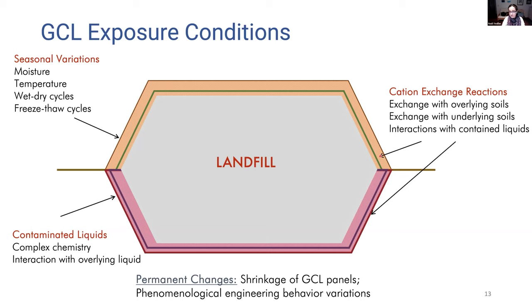Both at near surface as well as at depth applications, it's possible to have cation exchange reactions, exchange interactions with overlying as well as underlying soils, and also interactions with the contained liquids. All of these interactions may result in permanent changes in the behavior of the GCL, including the shrinkage of the GCL panels and changes in the engineering behavior of the material, decreases in the swelling capacity of the material, increases in the hydraulic conductivity, changes in Atterberg limits and such.